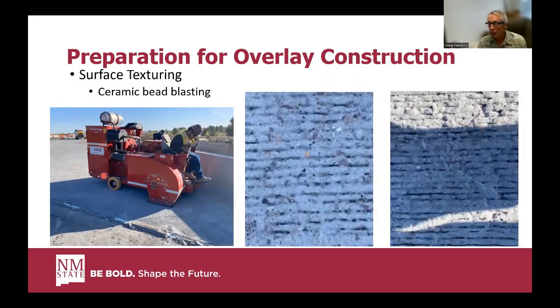So once they got the HPD layer down, we needed to do the surface prep. What you want on your surface is some exposed aggregate. So when you look at the picture here and you see some exposed fine aggregate from the ceramic bead blasting, that is kind of bare bones minimum as to what you want to see for exposed aggregate. So we accepted that as adequate, and it was really minimal in terms of acceptability.